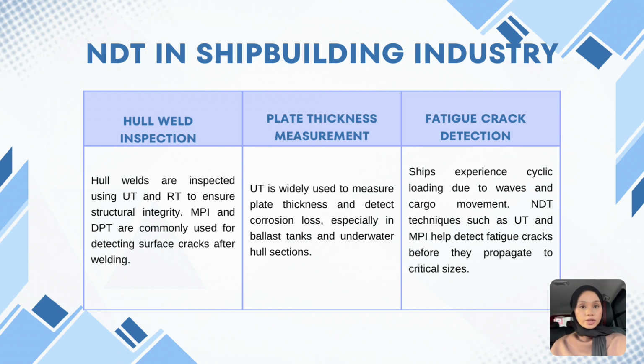For this slide, I will explain the role of NDT in the shipbuilding industry. The first one is hull weld inspection. The hull welds are inspected using UT and RT to ensure structural integrity. Additionally, MPI and DPT are commonly used to detect surface cracks after welding, which is important to prevent future failures. Second is plate thickness measurement.